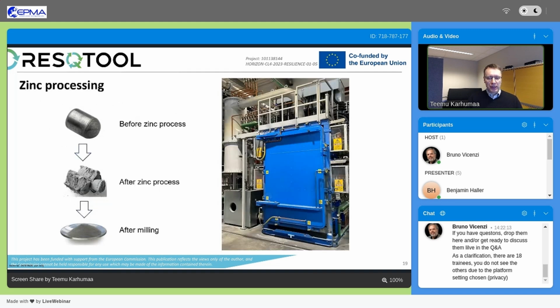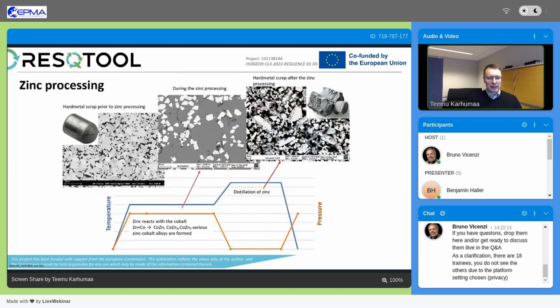And then we come to zinc processing. This is a picture from our production furnace at Ticomet. Zinc processing can handle only sintered hard metal scrap, and the hard metal scrap is put together with liquid, molten zinc into a graphite crucible, where the zinc alloys with the cobalt binder and causes expansion, a volume increase. After distillation, evaporation of the zinc, the scrap part can look like this in the middle, and this is very fragile and easy to grind to powder. If we look in a little more detail at the process, this microstructure of a mining tool on the left side can become something like this in the middle when the zinc is alloyed with the cobalt binder. So the tungsten carbide grains are pulled further from each other.